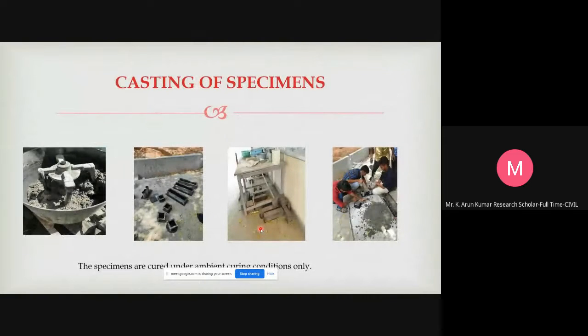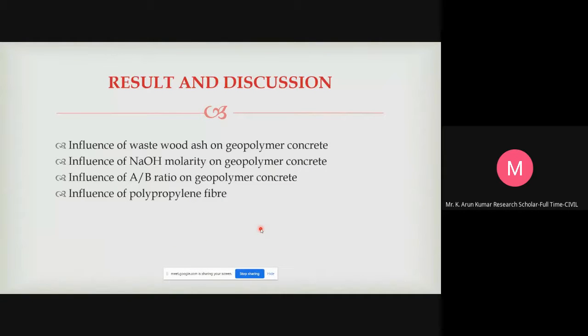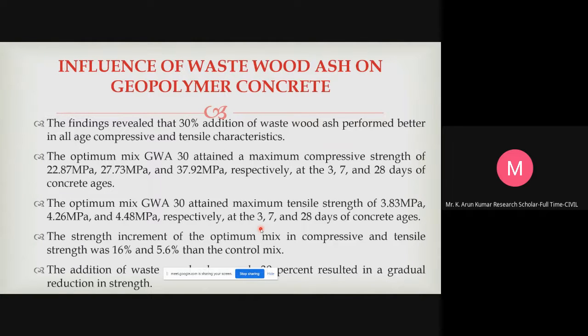This is the casting of specimens, and now we move on to the results and discussion. The results and discussion comprise 4 parts: the influence of waste wood ash on geopolymer concrete, the influence of NaOH molarity on geopolymer concrete, then the influence of A/B ratio, then the influence of polypropylene fiber. Regarding the influence of waste wood ash on geopolymer concrete, these are the findings after the results. We have found that 30% addition of waste wood ash is the optimum percentage, which showed maximum performance in all strength characteristics like compressive and tensile strength.